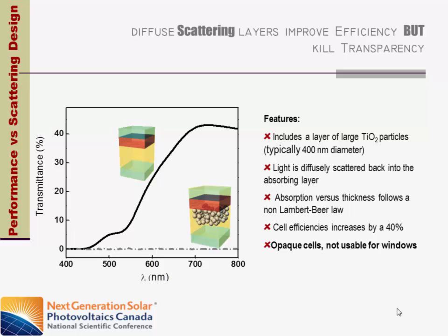And the reason for that is because diffuse scattering does not discriminate in wavelength. If I create disorder in my structure, although it can be done, it's a little bit sophisticated, in principle it's very difficult to have multiple scattering effects for certain wavelengths and transparency for the rest. So I cannot preserve transparency. I just create white light, it affects all wavelengths. Right? And this is what you see.